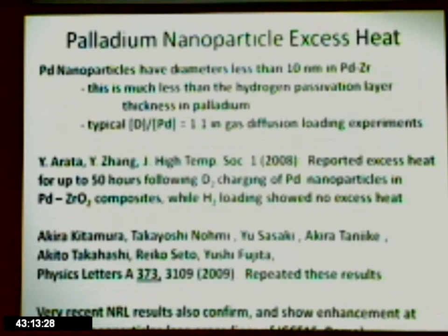Well, I think this is one thing that, at least to me, seems a lot more intriguing, and that's the possibility of palladium nanoparticle excess heat that's been observed now by a number of groups. These nanoparticles are less than 10 nanometers in diameter. In fact, the results get more apparent as the nanoparticle gets smaller and smaller, and many of these results have been taken for 1 nanometer or smaller particles. They're grown in a perovskite structure, which we'll discuss in just a second. And the point is the nanoparticle size is much less than the hydrogen passivation layer thickness in palladium.